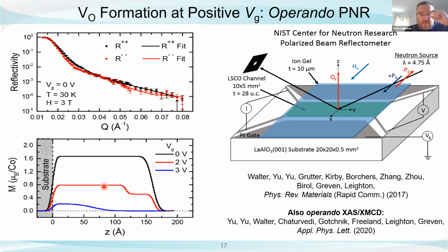So you can see, we allowed for a 2-layer model for the possibility that there's a little bit of a gradient towards the top. But basically, we're applying a surface electric field here, and we are, in fact, getting significant magnetization reduction caused by the formation of oxygen vacancies way at the bottom of the film. We can also estimate from this magnetization what the oxygen deficiency actually is, and we find that it's in really good agreement with what we got from synchrotron X-ray diffraction, okay?